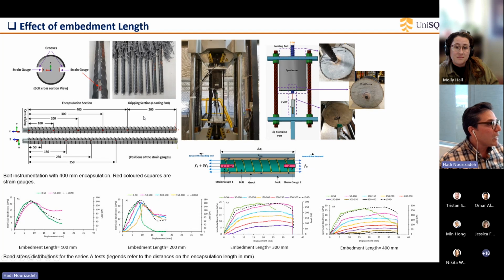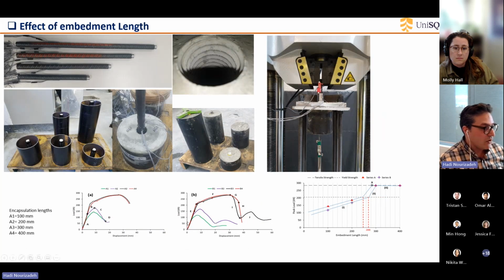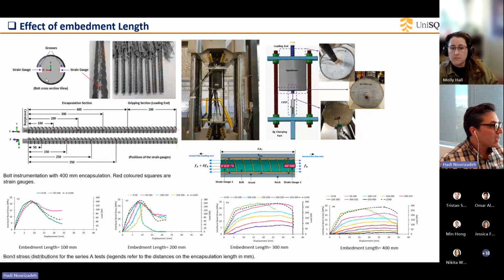To do more analysis, we instrumented our samples using strain gauges on both sides of the bolt. We made a groove on the bolts, machined them, and installed the strain gauges. Why? Because in this graph we see just the total behavior of this bolt, but we know that the bond stress behavior along this encapsulation length is different. To analyze these data, we need to analyze the strain behavior of this deformation and elongation of the bolt along the encapsulation length. To do this, as I said, we instrumented our rock bolts. Similarly, we installed them in the same type of concrete, carried out some pullout tests, and analyzed the data.